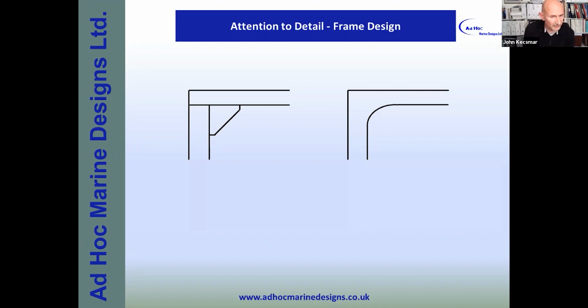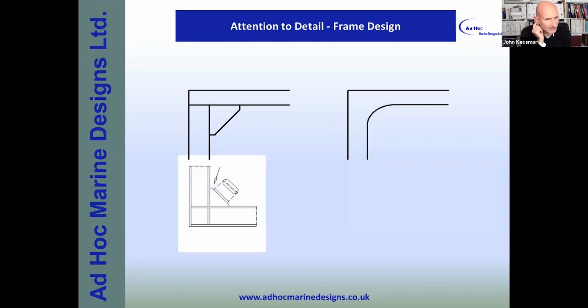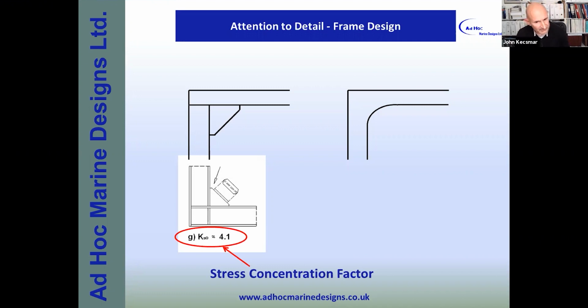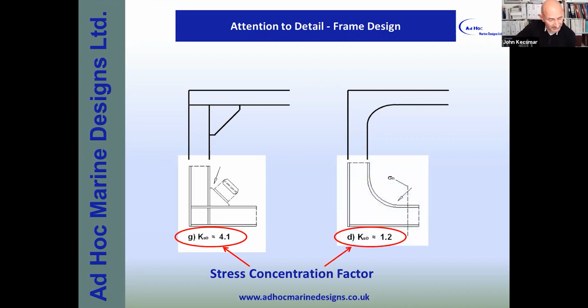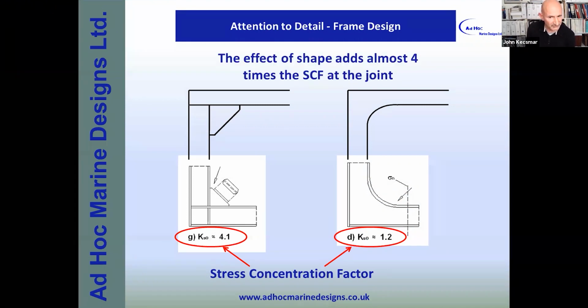But in terms of design, what merits do they have? The Japanese in the 1980s also asked this question of themselves, and they were looking at frame designs for various large vessels like container ships, tankers and bulk carriers. And so they came up with a series of very different types of connection, and they tested them to failure. And they established a stress concentration around the failure of the joint. And in this instance, the stress concentration factor is just over 4, whereas on the right, it's only just over 1. Quite a big difference. And so quite clearly, the shape of your frame can change the amount of stress by quite a significant amount. So that's something you need to bear in mind, not just in terms of cost.